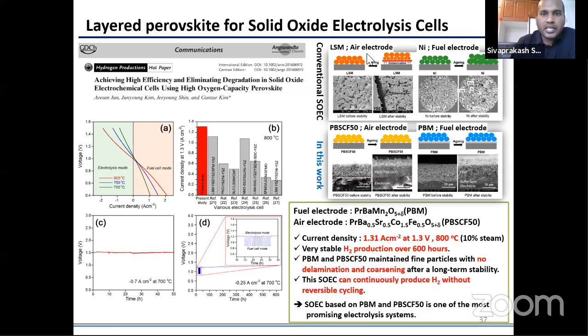But there are many other electrode materials available, like LSM. This LSM in electrolysis mode shows interfacial degradation. In this SEM, you can clearly see that due to oxygen buildup, there is a break happening between the electrolyte and the LSM electrode material. Because of this, the interfacial resistance will be very high, and the cell eventually breaks down.